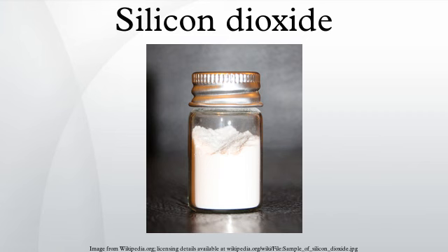Precipitated silica. Amorphous silica, silica gel, is produced by the acidification of solutions of sodium silicate. An initially formed gelatinous precipitate is then washed and dehydrated to produce colorless microporous silica. An idealized equation involving a trisilicate and sulfuric acid is shown: Na2Si3O7 plus H2SO4 gives 3SiO2 plus Na2SO4 plus H2O.